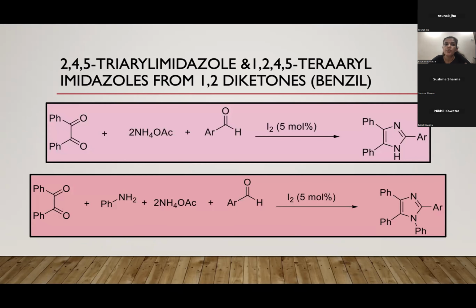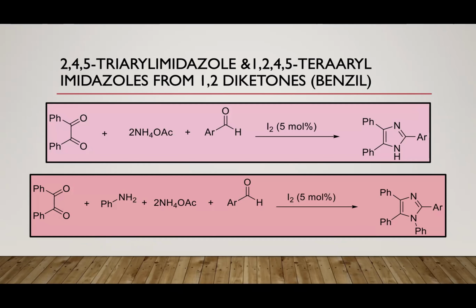We tried synthesizing 2,4,5-triaryl imidazoles and 1,2,4,5-tetraaryl imidazoles from 1,2-diketones. In this broad program of developing a library of imidazoles, we explored the catalytic activity of iodine. We report a simple, rapid one-pot procedure for 2,4,5-trisubstituted imidazoles and 1,2,4,5-tetrasubstituted imidazoles. The reaction was carried out using benzil, a 1,2-diketone, aniline, ammonium acetate, benzaldehyde and iodine, with the solvent ethanol at room temperature.